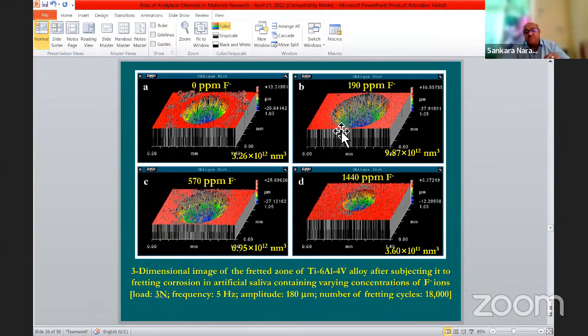So the fluoride ions started attacking the material. Generally, magnesium is good in fluoride medium. Titanium is very bad in fluoride medium. The moment you bring titanium into contact with fluoride, it will immediately attack. So the fluoride started attacking and developing a bigger hole in that.